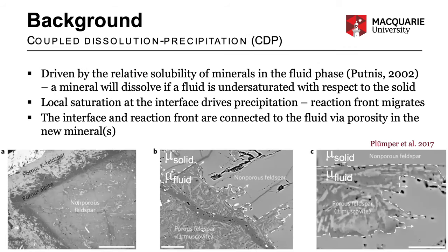The coupled dissolution precipitation process is driven by the relative solubility of minerals in the fluid. And so any mineral will dissolve if the fluid is undersaturated with respect to that mineral. This is true of all fluid-mediated metamorphism in general. Local saturation in a boundary layer fluid will occur at the interface because the process just dissolves components of the mineral into that boundary layer fluid. This ultra-local saturation in the boundary layer fluid then drives precipitation. The reaction migrates inwards into the reactant mineral via porosity, so the fluid can get access to the internal parts of the crystal. So porosity is an integral part of the coupled dissolution precipitation process.